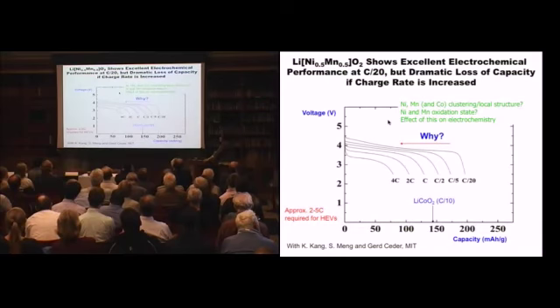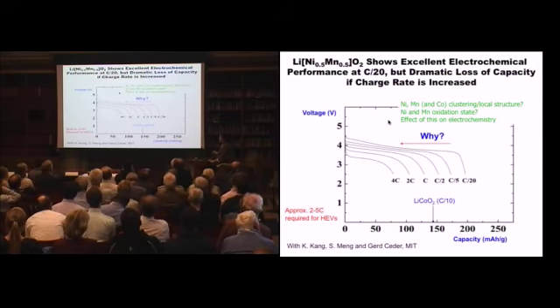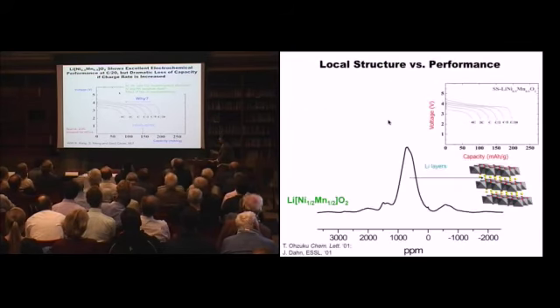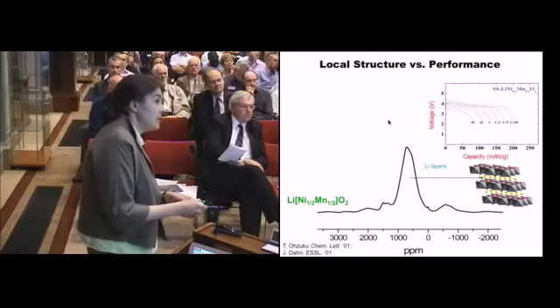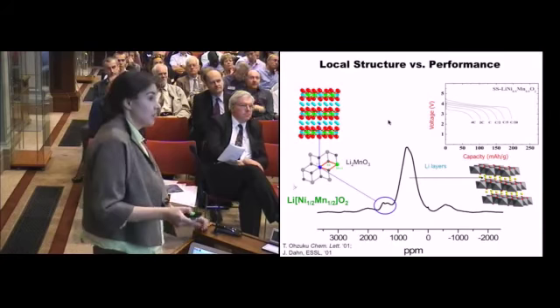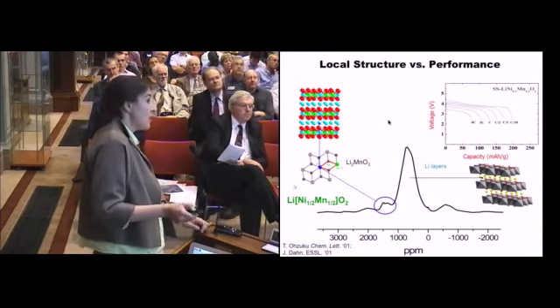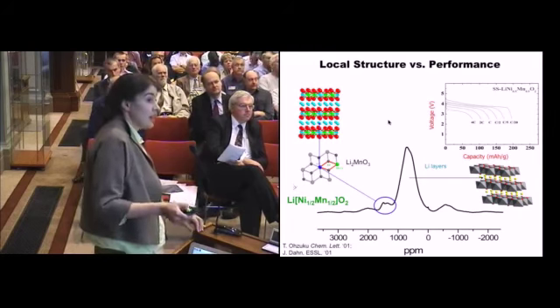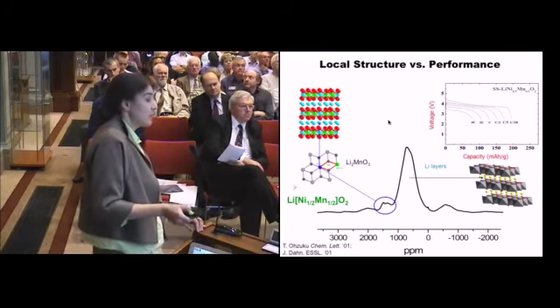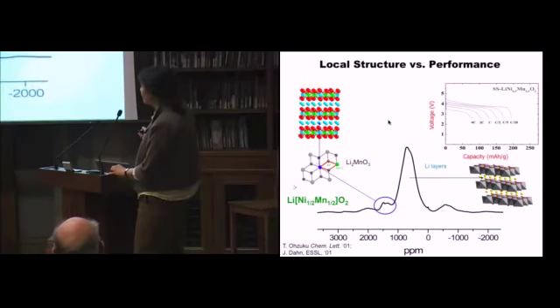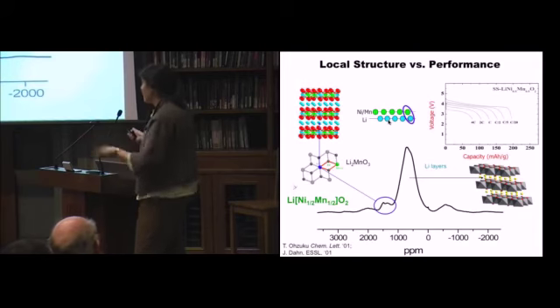But if I charge fast at 4C, which corresponds to pulling the charge out in 1 hour divided by 4, so 15 minutes, you can see the capacity decreases significantly. So the question is why? What we did was to examine the local structure of this material. So here again is the NMR spectrum of the material. By looking at model compounds, compounds where I know the structure, I can assign this peak to lithium in the layers. And this peak, it turns out, happens to be from the lithiums that are moved from this layer to this layer. So they've swapped. Lithium and nickel are about the same size, so when you make the material, they can swap and form defects of nickel sitting in the lithium layers. And this nickel stops the lithiums moving rapidly through the layers.